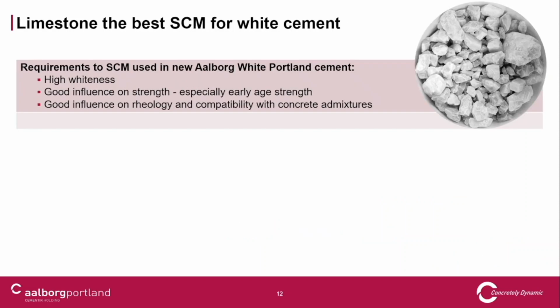So why limestone? Why is that the best option for our cement, rather than slag or something else? We need a replacement material with high whiteness. We need a material with a good influence on strength, especially early strength—we'd like this cement to have good early strength, and often when you put in a pozzolanic material, you reduce early strength.